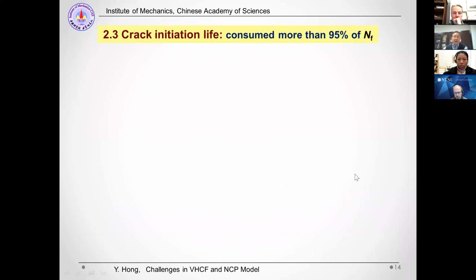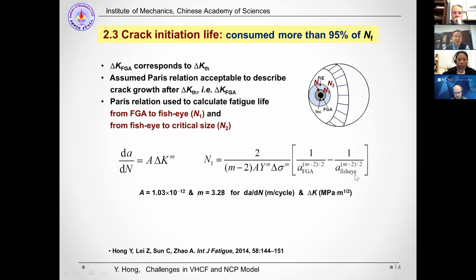And then the third point is about crack initiation life. We have mentioned previously the delta K value as a threshold for crack initiation. And also we assume the Paris relation can be used to describe the crack growth after the initiation, that is after delta K FGA. Then we can use the Paris relation to calculate the fatigue life from the boundary of FGA to the fisheye, and then from the fisheye to the critical size.